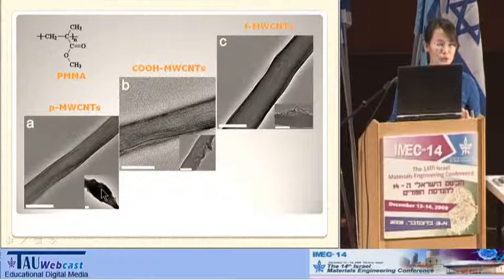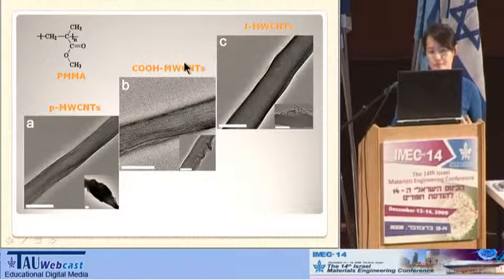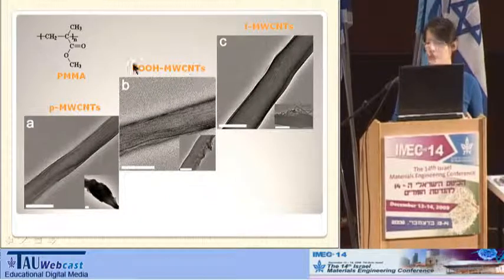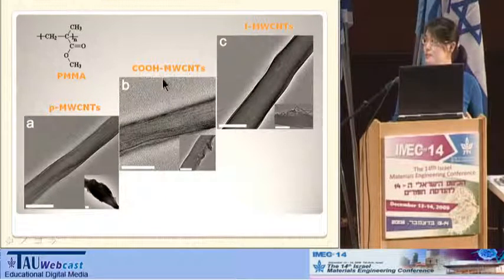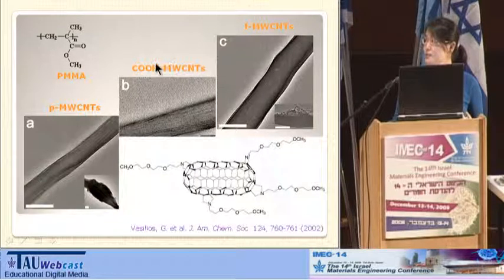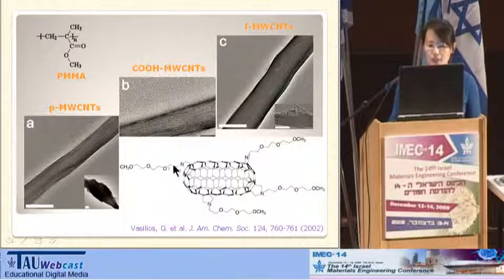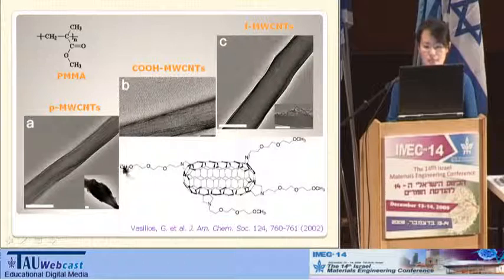In order to improve the dispersion and also the interface between the carbon nanotubes and the polymer, we decided to use some kind of functionalized carbon nanotubes. Here we use the carboxylated nanotubes and also another kind of functionalization. We have a collaboration, and this group produced some carbon nanotubes by the 1,3-dipolar cycloaddition reaction. And here we can see this functional group